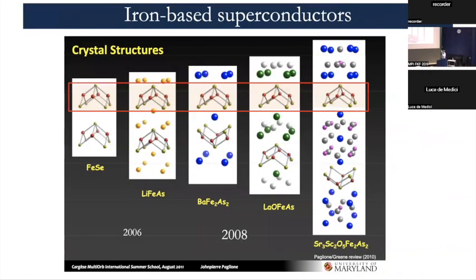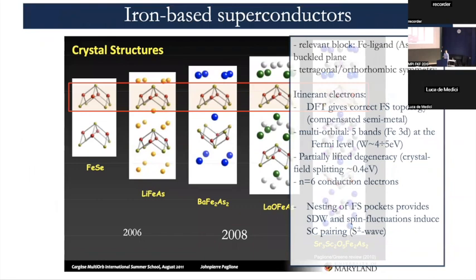So let me go now to the motivation of our studies of Hund's metals, which are iron-based superconductors. Iron-based superconductors have a structure of iron planes with ligands in between and some cations providing charge. The main structure is 5 bands at the Fermi level of 3d character coming from iron. They disperse 4 to 5 electron volts before renormalization due to correlations, and they have a partial lifting of the degeneracy. So all 5 orbitals participate in the conduction bands, and they host, in typical stoichiometry, 6 conduction electrons.